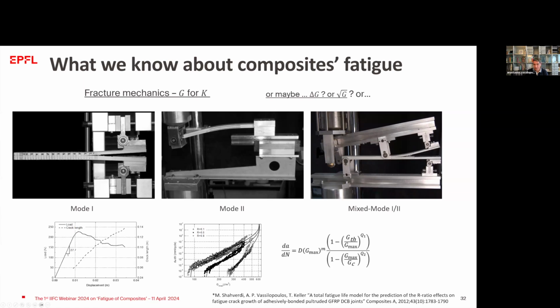And you see that in a lot of cases in these graphs, we have a kind of a fatigue threshold. We have a kind of bending in the curve when we approach values of 10^-6, 10^-7, which means that the crack propagates 1 millimeter every 10 million cycles. In this case, 10^-7, for a normal application, this can be assumed as a fatigue threshold, that the crack does not propagate anymore.